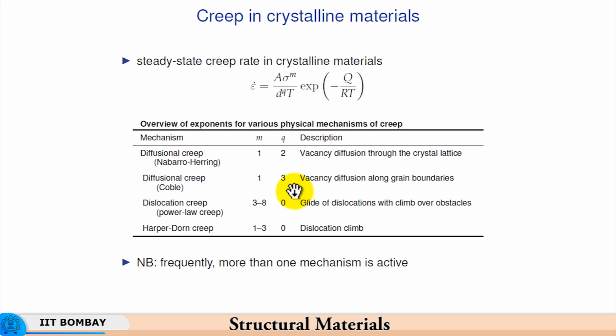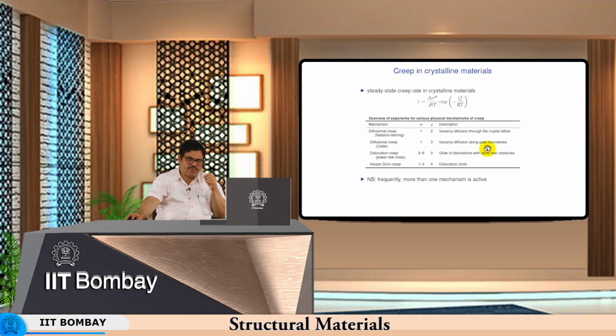and therefore, vacancy diffusion along the grain boundaries will also take place at high temperatures, like diffusional creep in Coble creep. So, creep will always have vacancy diffusion along grain boundaries, but at even higher temperatures it will have diffusion through the crystal lattice as well. So, let me put it that way: vacancy diffusion along grain boundaries will always be present, but at higher temperatures the vacancy diffusion through the crystal lattice will also take place, because there is sufficient driving force in terms of temperature to allow diffusion of vacancies through the crystal lattice, through the grains basically.